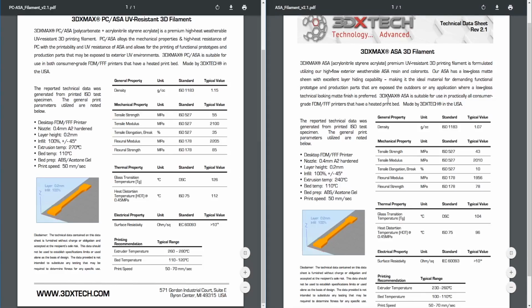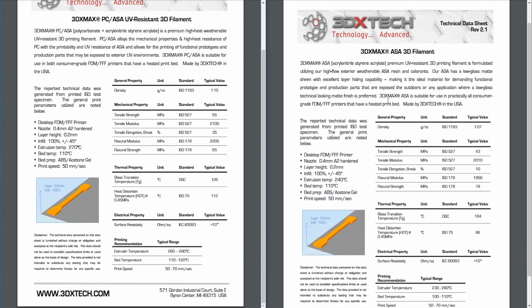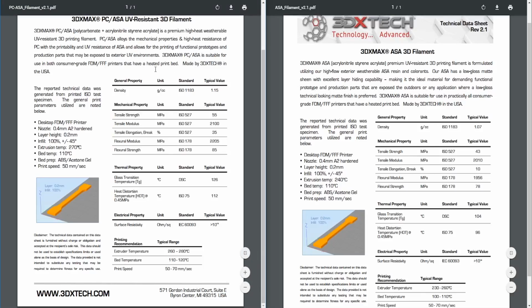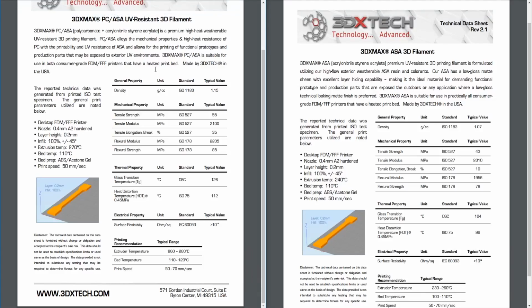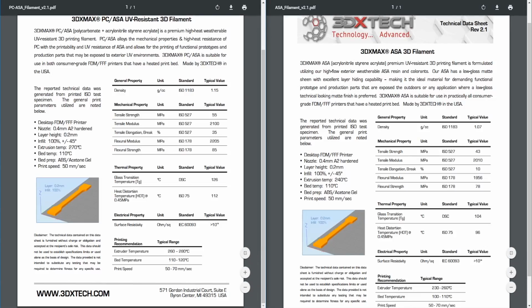But again, the difference is that the ASA, I believe the polycarbonate is not that good at UV. I think ASA is developed for that UV resistance. So I think the polycarbonate is going to affect the UV resistance, while this guy is completely ASA, is full ASA. So 100% of ASA's UV resistance it will have. This will only have 50% or whatever the mix is, like 60 to 40 or 70 to 30. Whatever the mixture, that's the total resistance of ASA's UV resistance that you'll get. This is 100%, this is whatever the mix is.